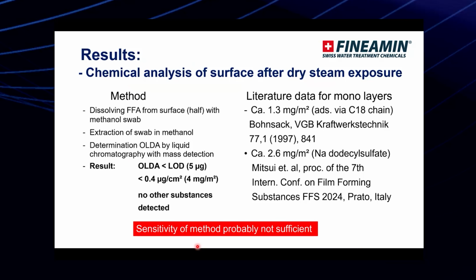We also do chemical analysis on the surface after dry steam exposure, using liquid chromatography with mass detection. What we do is try to dissolve the FFA from the surface: one half of the specimen with a methanol swab, and then we do extraction in methanol, and we determine the OLDA by liquid chromatography with mass detection. Unfortunately, we could not see the results. In fact, nothing was detected, and I think we can say the sensitivity of the method is not sufficient to see the results, because it is not sensitive.